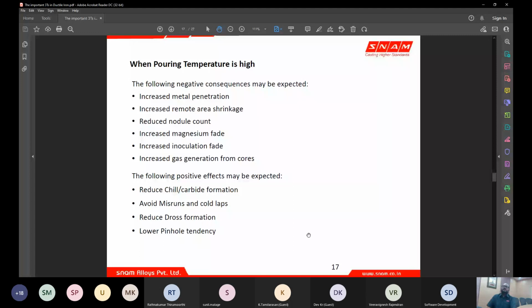So these are the effects when the pouring temperature is high. We get penetration defects in the molds, like increased metal penetration. It can lead to increased remote location shrinkage, because you're going to have the liquid metal inside the cavity hotter for a longer time. So that means more hot spots, and then more shrinkage coming up. Reduced nodule count, because your nuclei are going to be dissolved again into the liquid metal because it is kept at a very high temperature. Your magnesium fade is high, your inoculation fading is going to be high.